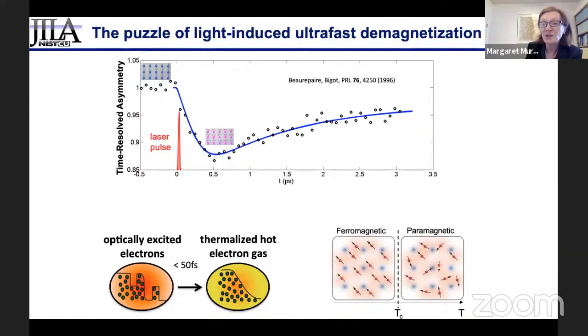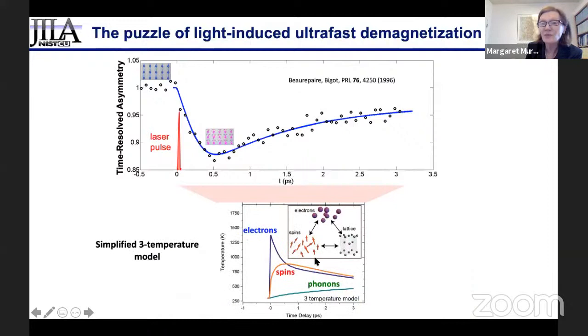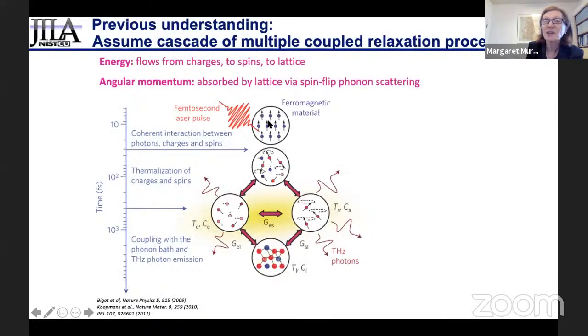And so because it took such a long time, people speculated that the bottleneck must be how long it takes the angular momentum to dissipate as the sample changes from ferromagnetic to paramagnetic. And so this is the origin of some of these three temperature models used in magnetic systems. So essentially, the idea was that the light coupled to the charges quickly, but it took a lot of scattering processes to absorb the angular momentum. So it was a cascade of multiple coupled interactions.